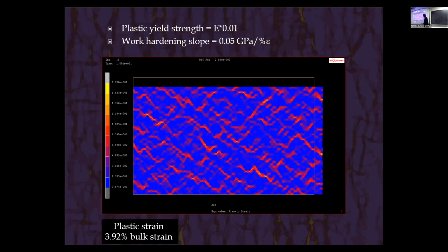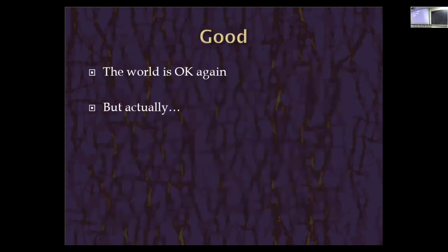is as I get my little plastic shear localization, they actually fatten out. So the more I push, the fatter they get. So it's not like I have homogeneous plastic strain. I still have shear localization, but it gets really hard to drain it enough to get shear localization through the whole model because these just get fatter and fatter, right? So they spread out. So, okay, good. We're back to where we should be. We have now reproduced that plastic deformation does not shear localize.